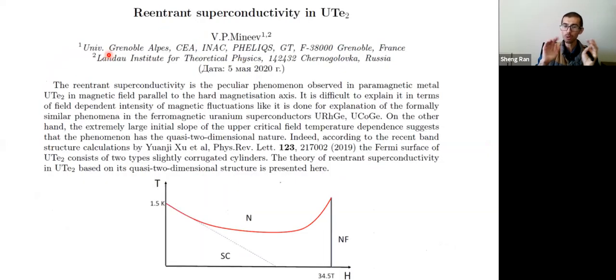Based on this quasi-2D band structure, someone proposed that if you have a quasi-2D structure, when you apply the magnetic field, when the field is really strong, you can confine the electrons within the plane, and therefore you do not have closed orbits. In that case, the orbital effect will not play a role. Then you can have field-induced superconductivity.